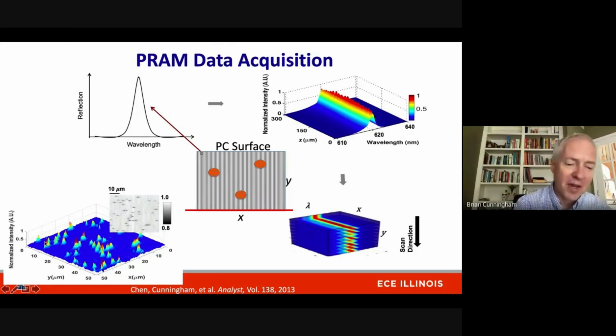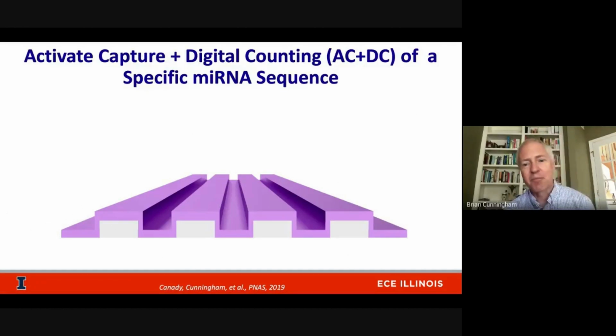We can see each one very clearly. We can represent them mathematically on a 3D graph as shown here, where it's more intuitive to show them as peaks rather than dips. But keep in mind, each one of these nanoparticles represents a dip, a reduction in the reflected intensity. So we sought to take advantage of this to perform a very high sensitivity and simple assay for microRNA. So now kind of returning to our clinical problem a bit.